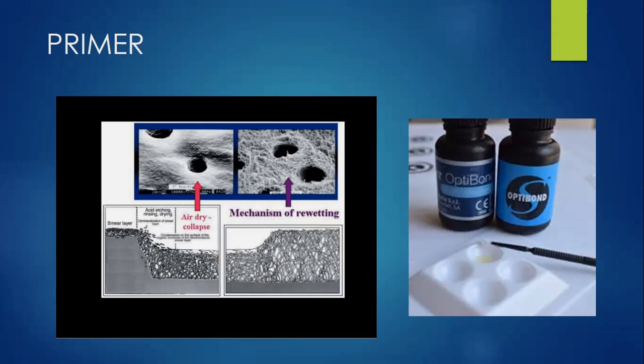Because if excess water is there, it allows phase separation of the phobic and philic components. It will result in the formation of blisters and resin globules at the resin-dentin interface. And if it is desiccated, it will lead to collapsed collagen and incomplete intertubular resin infiltration. The interface is characterized by an infiltrated area and a superficially forming hybrid layer. If we are not able to penetrate the resin into these spaces, we'll have a very thin hybrid layer that won't have a good life. The primer solvent should be able to displace all the water trapped within the collagen network, allowing monomers to interdiffuse.